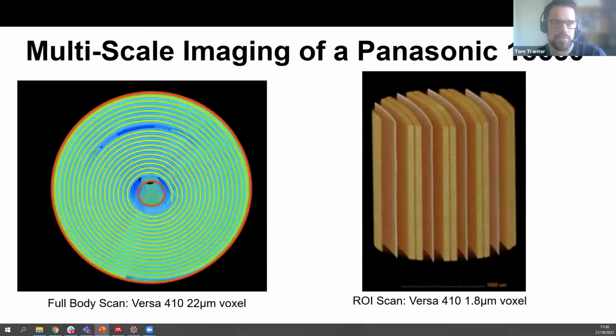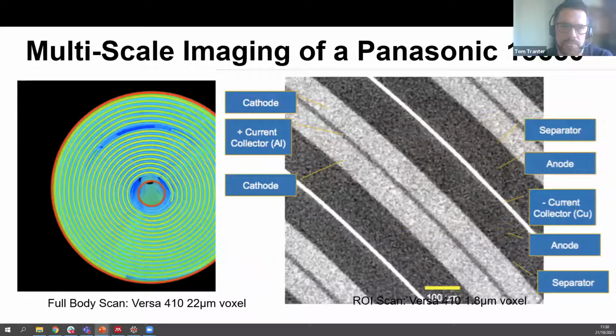On the larger scale, we have also done quite a bit of work looking at these jelly rolls and layered structures in other types of batteries. We can pick out all of the layers pretty easily. They attenuate the X-rays in different ways, so the different materials appear as different colors. The brighter one is the cathode, and in the center you have a current collector running through it. The darker one is the anode and another current collector, and that bright current collector is copper and the other one is aluminium. So you can build up these images and then analyze how these layers change over time. As the cell charges and discharges, you get slight expansion and contraction, and that of course changes the acoustic properties as well.